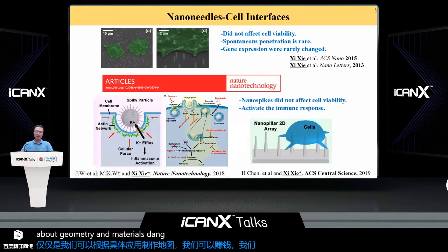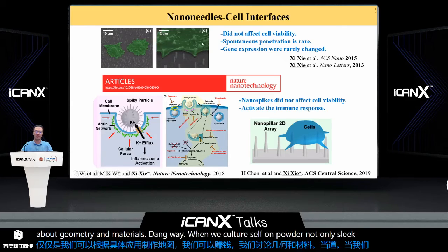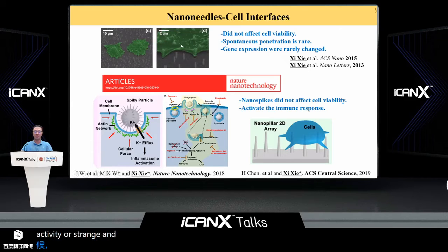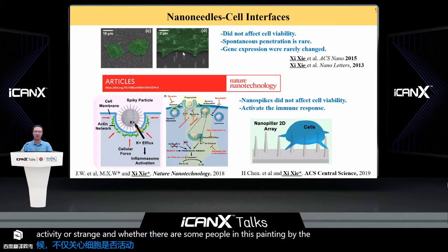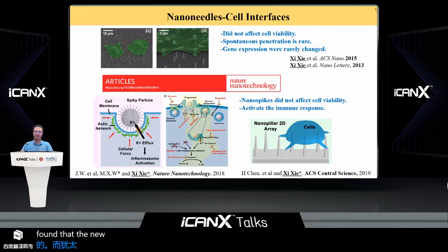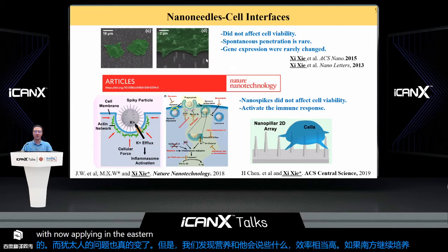Then when we culture cells on top of the nano needles, we basically care about whether the cell activity was changed and whether the cell membrane is penetrated by the nano needles. Based on my previous study, I found that the cell viability is not affected and the gene expression is not really changed. However, we found that the penetration efficiency is quite low if the cell was cultured on top of the nano needle array without applying any external force. Therefore, we conclude that external techniques are required to enhance the penetration.